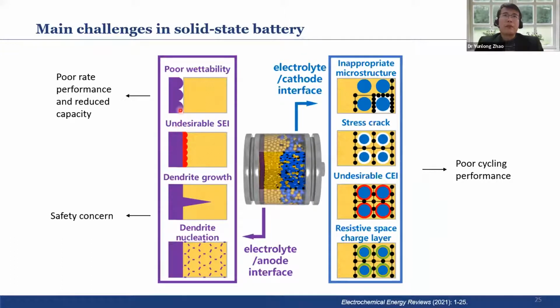But sometimes, because of a poorer interface, it can generate some undesirable SEI, and also dendrite growth. I will explain later. So this could still be a problem for the lithium in solid state electrolytes, especially if the electron conductivity is high. So this is related to the anode side.